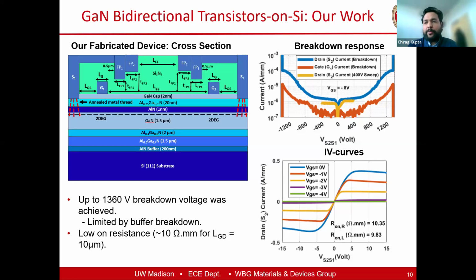We were able to get around 1200, 1300 volt in both direction. And on the same transistor, because this is catastrophic breakdown after 1300 volt, I'm showing here in this yellow curve that you can sweep the same device 400 volts in either direction, and it will hold. So we obtained around 1360 volt breakdown in this, and we were able to get that for 10 micron of LGD with a low on resistance of 10 ohm millimeter.